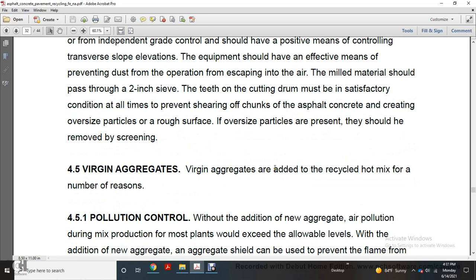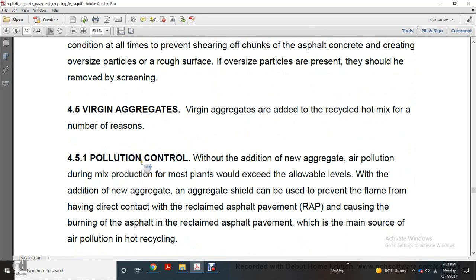4.5 Virgin aggregates are added to the recycled hot mix for a number of reasons. Pollution control: with the addition of the new aggregate, air pollution during the new mix production is reduced. Most plants would exceed the allowable level without the addition of new aggregate, which is used as a shield to prevent the flame from having direct contact with the reclaimed asphalt pavement,